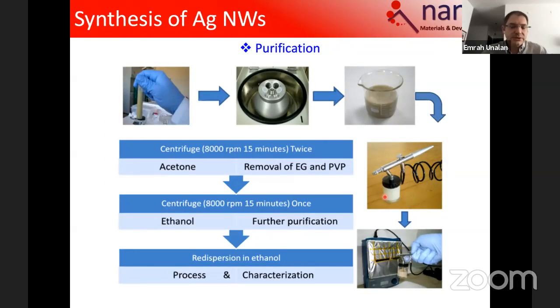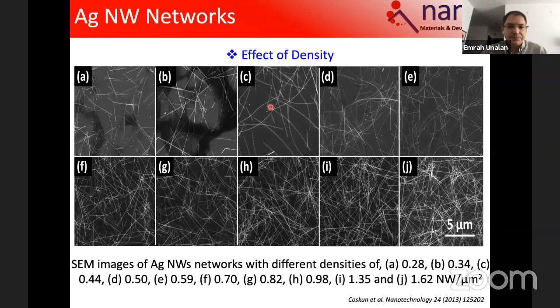After the synthesis, solution-based methods are used for their purification because we have some polymers to get rid of. And we also have some particles, since the synthesis doesn't give 100% nanowire growth, but you have some particles on the side, so you need to remove them. If it is small-scale synthesis, centrifuge might work, but if it is gram or liter scale in solution, that might need to be taken care of using some other methods rather than centrifugation.